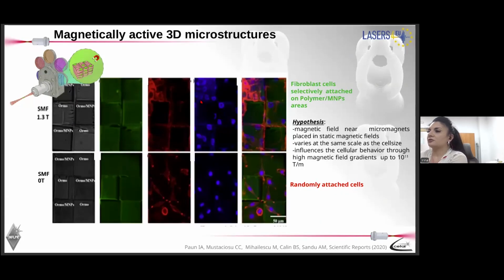The in vitro tests showed the following conclusion. If we have no magnetic field applied, as I told you in the first slide explaining this experiment, the cells attach all over without any kind of preferential attachment. On the upper side, we applied a static magnetic field. The cells mostly attach on the squared magnetic areas. The better view is here, where you see only the cell nuclei marked with Hoechst, because we also have autofluorescence of our photopolymer, which disturbs the whole image a little bit here, where you can see the cells in red. But the one with blue cell nuclei is very suggestive.